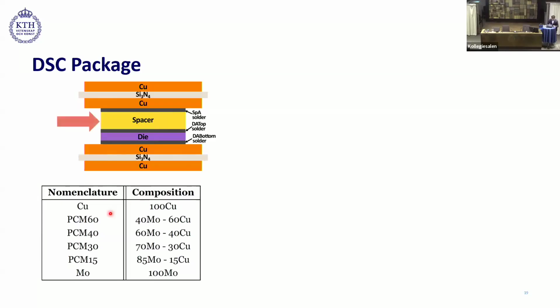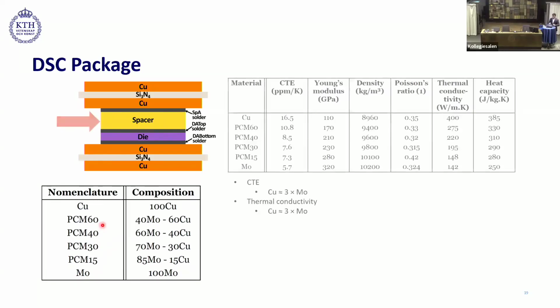We used spacer materials that were composed of different percentages of copper and molybdenum. And depending on the percentage of copper material we have inside the spacer, this number varies. So basically, 60 here represents 60% copper. Since copper has 3 times higher coefficient of thermal expansion than molybdenum and 3 times higher thermal conductivity than molybdenum, the thermal and the mechanical properties of these spacer materials will also vary with the percentage of copper and molybdenum inside them.